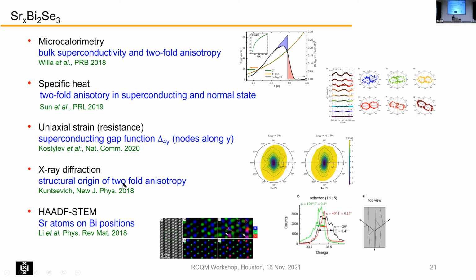Then X-ray diffraction indicates that there is some crystal inhomogeneity, in the sense that the C-axis in the crystal seems to wobble around a little bit. So you have some kind of, I would not call it grain boundaries, but you have smaller crystallites. And from transmission electron microscopy, also for this material, it's clear that not all the atoms are intercalated.